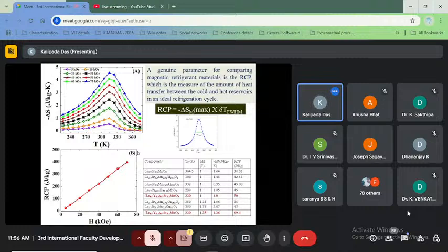So we get in this case almost 400 joule per kg relative cooling power for this yttrium doped lanthanum strontium manganite sample. And the other reported samples are also there with their relative cooling power. So our sample shows a moderately large magnetocaloric entropy change, so it can be considered as a good refrigerant material.